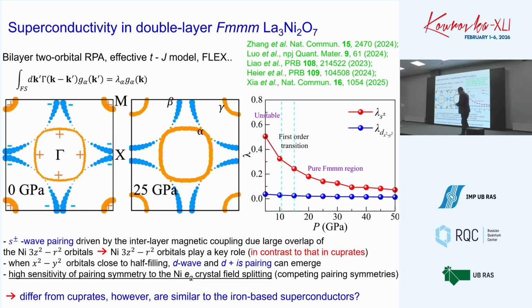And on this aspect, I found a very nice paper by Thomas Maier about just the bilayer Hubbard model. He claimed about 3 years ago, he computed just a model, and he tried to tune the Fermi surface by doping it. He claimed that as soon as one of the Fermi surface sheets disappears, this leads to a rise of superconductivity in this material. If we would dope this material with electrons, we remove this Fermi surface sheet. And possibly this is the way to pump superconductivity in this material.